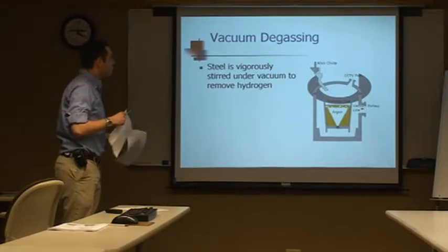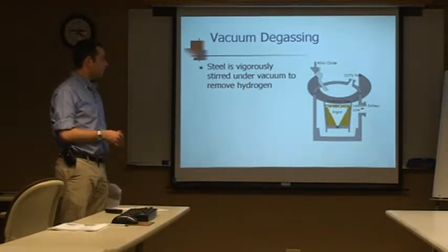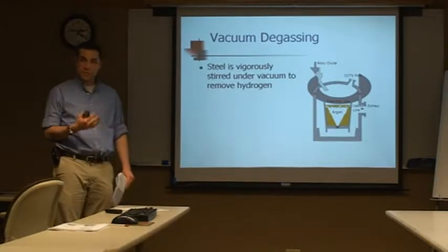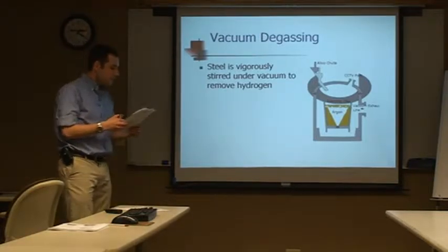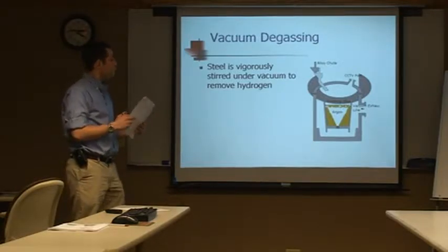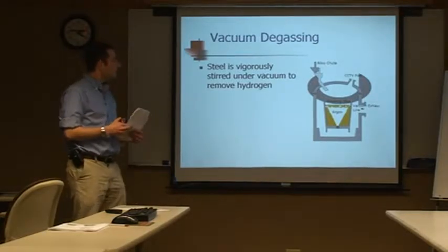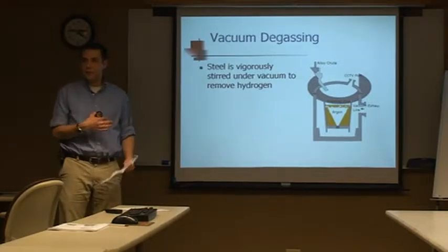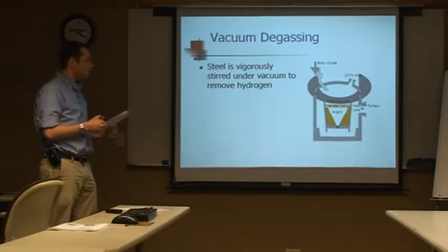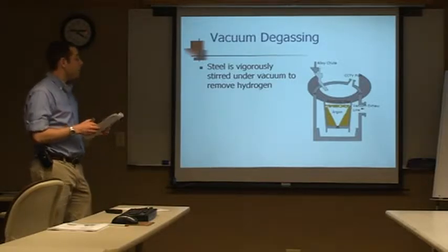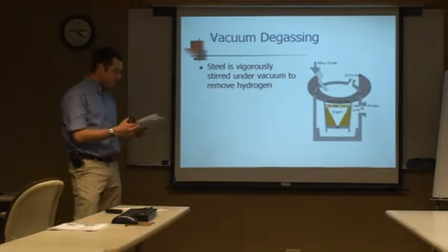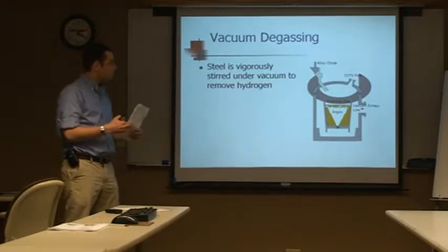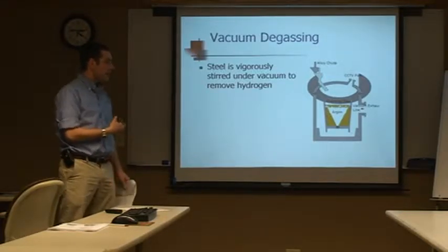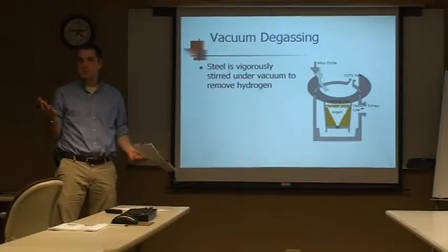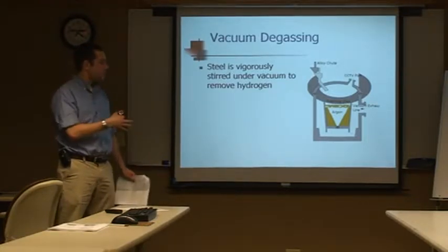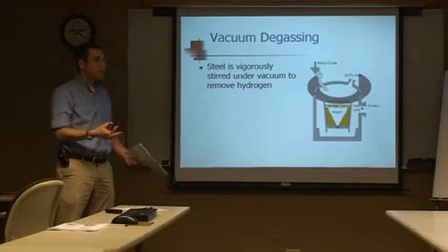So after we have the alloys or the grade chemistry mixed up to where we like it, we send it over to the vacuum degassing station. The vacuum degasser has one main function, and that is to get hydrogen out of our melt. Hydrogen is along the same lines as phosphorus, in that it's always bad for steel, but it's very hard to get out of steel because hydrogen is the smallest element, right? So it just sits in the steel and hides, and makes it really hard for us to get out.